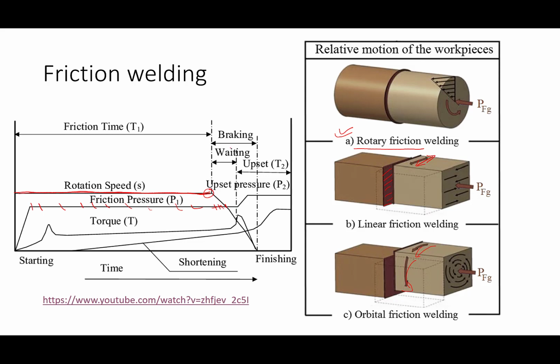If you see the time versus rotational speed, during this braking time period the speed is coming down. Certainly it will not become a standstill immediately. Somewhere in between the start of the braking and the end of the braking, where the RPM is reduced to 0, the upsetting pressure or forging pressure is applied. So first friction pressure and then upsetting pressure. This is not immediately after the application of the brakes, but somewhere in between zero speed and the commencement of braking.